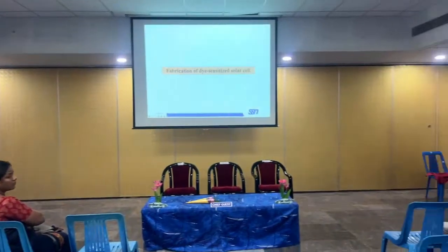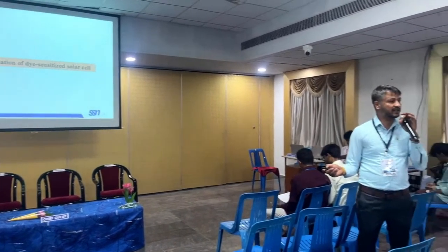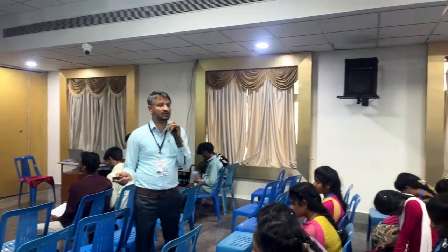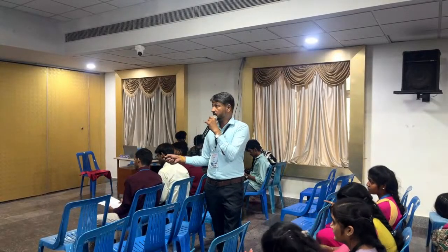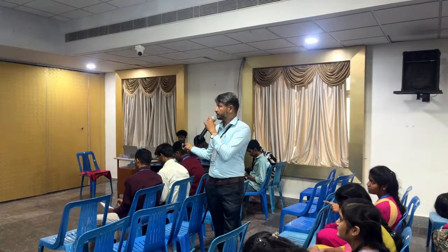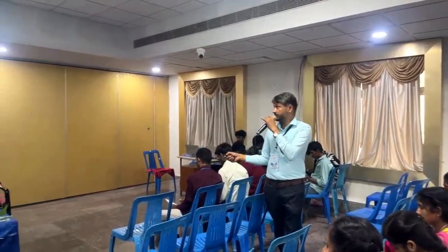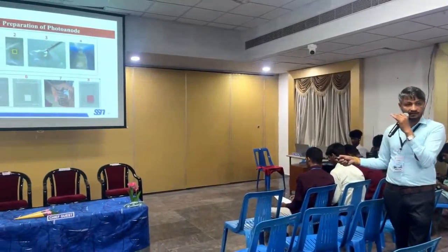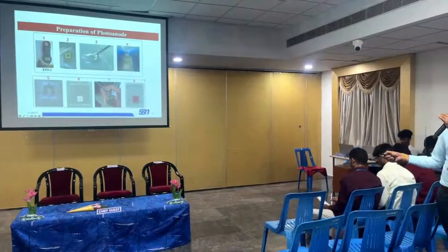So, we discussed making TiO2 rods and particles, a mixture of rods and particles, with one method called the hydrothermal method, a solution-based method. Now we are going to see how to fabricate solar cells, dye sensitized solar cells. So this is the TiO2 powder, synthesized powder, which has to be ground to make a slurry of TiO2 with some chemical. First we place our FTO substrate. As I said in the beginning, the FTO substrate is glass. It is transparent as well as conducting. So we placed our slurry over our FTO substrate. Then, with the help of a blade, we coated it.